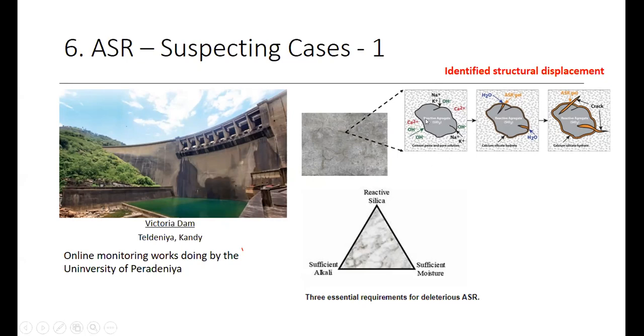ASR means, as we discussed previously, we have to utilize aggregates, mainly, in concrete. So the coarse aggregates are there. Sometimes they might have reactive silica. And with the cement, there will be hydroxyl ions, sodium ions, and some cations like calcium, potassium, sodium. With these reactive silicates, there can be a reaction with those cations, and they will form some secondary alkali-silicate hydrate. And the aggregates also can form, with this reaction, a gel. We call it ASR gel, inside this aggregate. That also forms cracks, which are much similar to the cracks that we can see with the DEF formation.